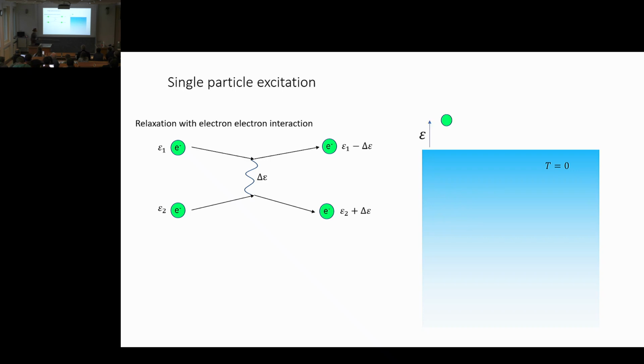And single particle excitation would be, for example, adding an electron to the Fermi sea with particular energy epsilon above. And the idea, first order idea, is we have to look at what electrons it can scatter with, which is actually not that many, because if it has an energy epsilon above the Fermi edge, it can actually only interact with a thin slice on the edge of the Fermi sea, a thin slice with a width of epsilon. So if we assume constant density of states and everything, that's a factor of epsilon.